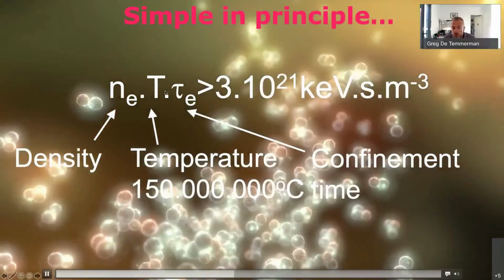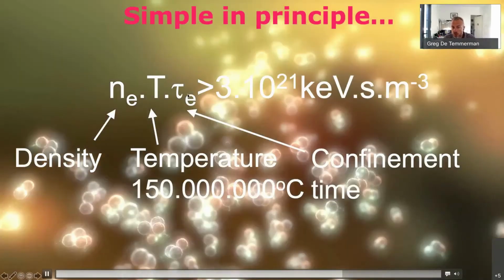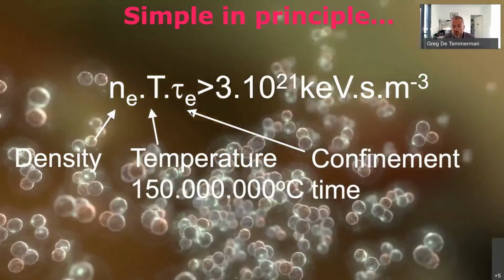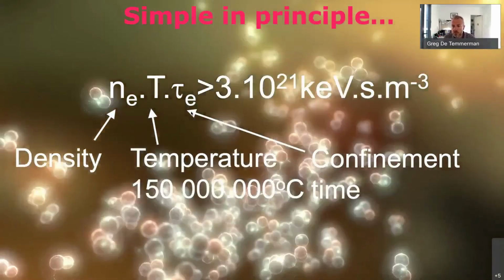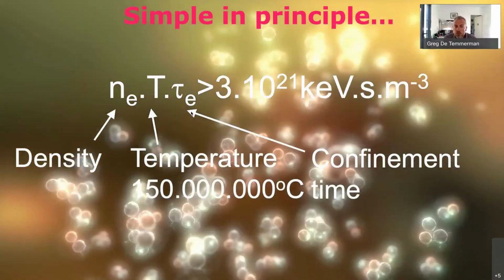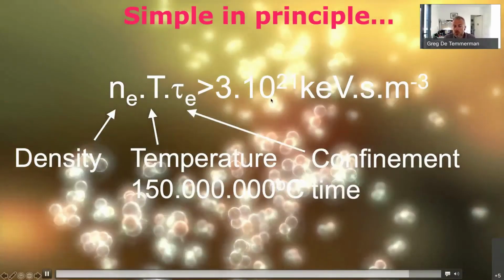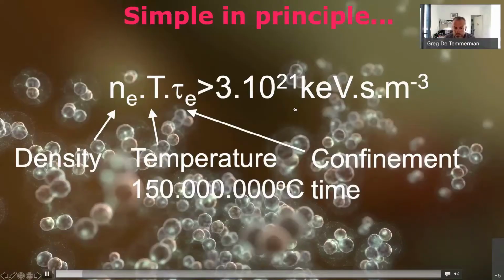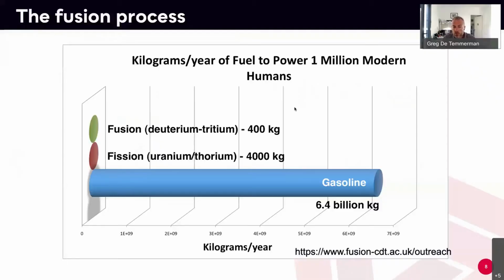We use high temperatures again, and we use relatively long confinement time. So confinement time for a plasma physicist, or long confinement time would be in the order of seconds, right? For us, it's already quite a lot. But if we can get those parameters right, then we get fusion to actually happen. Fusion is very interesting for many reasons. First of all, it's safe because it's so hard to make fusion to happen. It cannot run away by itself.